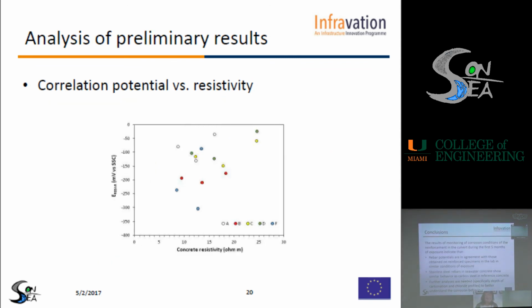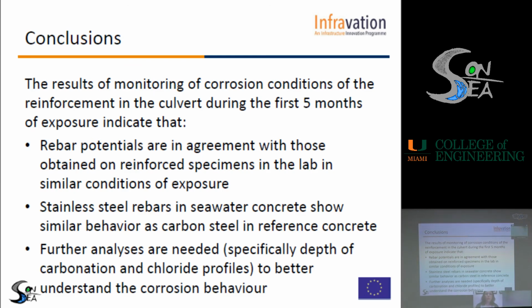So the conclusions of my presentation are that the results of monitoring of the corrosion conditions during the first 5 months of exposure indicate that the rebar potentials are in agreement with the ones that we obtained on reinforced specimens in the lab in similar conditions of exposure. Stainless steel rebars in seawater concrete show a very similar behavior as carbon steel in reference concrete, and we can assume that they are both not corroding yet.